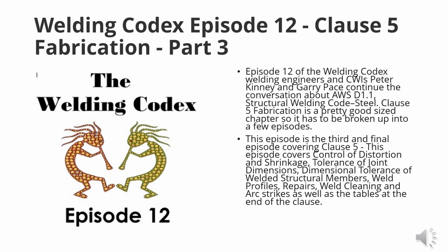Gouged grooves produced by gouging shall be in substantial conformance with groove profile dimensions. Okay, so that gets us back to these figures. Suitable access to the root shall be maintained. Yeah. So what this is, there are multiple methods now of gouging. Before you just had straight up carbon arc, but now you have plasma gouging. Basically, when you're doing gouging, try to make it a nice consistent gouge to facilitate the welding of it, and try to make the gouges similar to those figures. The better you can make your gouging, the less grinding you do, the cheaper it is. If you're going to remove it, like you say, keep it to a minimum because time is money on that stuff.